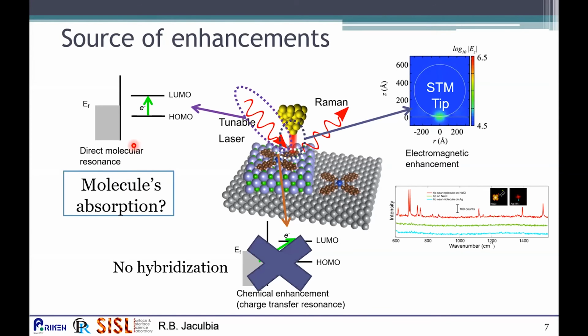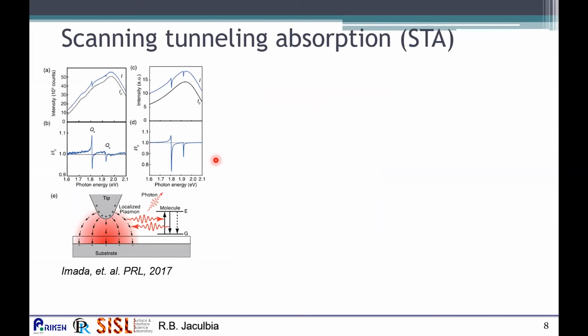Fortunately, in the single molecule case, our group has developed a technique that can measure the single molecule absorption, reported in this paper in 2017, wherein we use the localized plasmon generated at the tip-metal junction as a kind of light source, as it is used in conventional absorption spectroscopy. And then the light produced by this localized plasmon is absorbed by the molecule. Our member was able to show that the sharp transitions correspond to the absorption of the molecule. Then we applied this technique to our system.